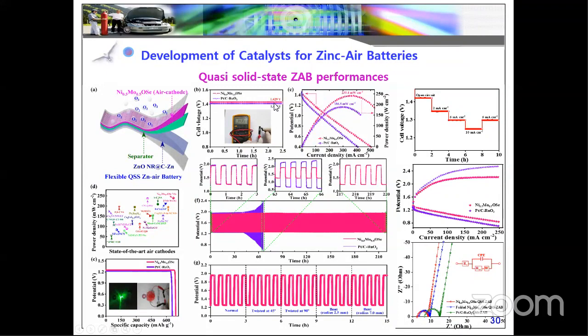Our catalyst shows a higher OCV compared to the commercial one, and you can see the value on this display, almost 1.43. And the power density, this is the IV curve. In the last talk I saw solar cells, where they are also doing IV, the potential and current varying studies. When we change the current and the potential, we can get the discharge curve, and from the discharge curve we can get the power density. The nickel, molybdenum, and zinc nanorod based devices achieved higher power density compared to the